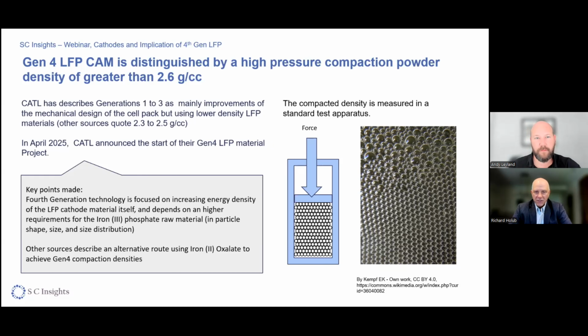Well, what is compaction density? Quite simply, a small amount of powder is put into a press cylinder, almost like a tablet press, and force is applied, and you measure the weight and the volume at the end of the pressure being applied, and that gives you the calculated compaction density. There are a variety of vendors providing this kind of equipment out there. If you wanted to do some work in your development, this equipment's readily available.